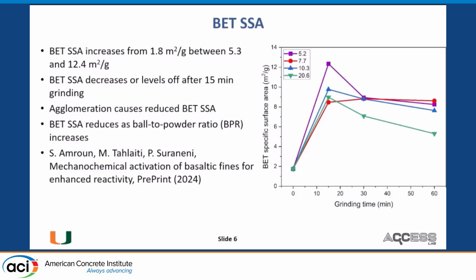So what we see is a very classic mechanochemical response in that the specific surface area increases. It actually increases very, very rapidly. And then it goes down, or it levels off, after, in our setup, at least 15 minutes of grinding. So we are attributing this to various sorts of agglomeration, aggregation, and similar properties. I will be the first to admit we don't have a full handle on the nature of these agglomerates or aggregates. We will at some point.